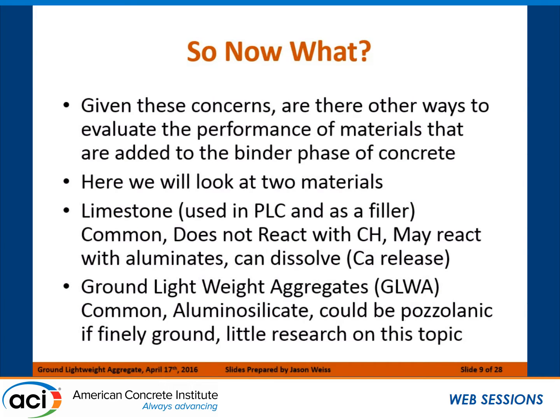And the two materials that we're primarily going to be looking at here are limestones, whether we're using a Portland limestone cement or whether we're using the limestone as a filler. All right, and in this particular case, we don't expect a lot of reaction with the calcium hydroxide. We may have some reaction with the aluminates, and more importantly, we may get calcium dissolving into the system and changing the pore solution composition.